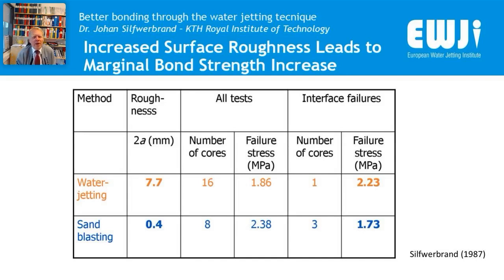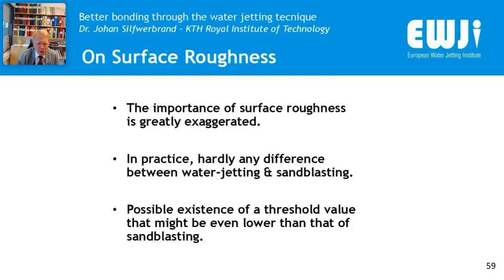We always have bond failure as a tensile failure, and we always have a lot of scatter. So water jetting is as good as sandblasting, but you cannot use sandblasting to remove concrete, because you only take 1 millimeter by using sandblasting. But here you can see that the roughness has a very small influence. The water jetted surface is about 19 times rougher than the sandblasted surface. So the importance of surface roughness is greatly exaggerated. In practice, hardly any difference between water jetting and sandblasting.